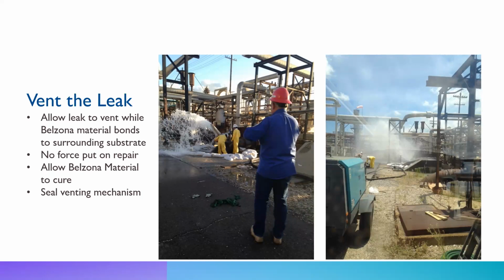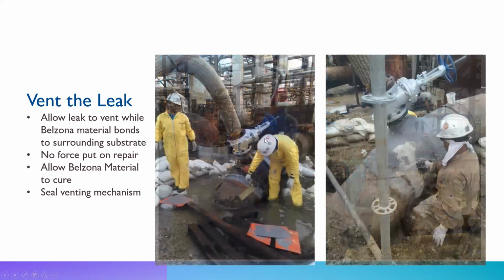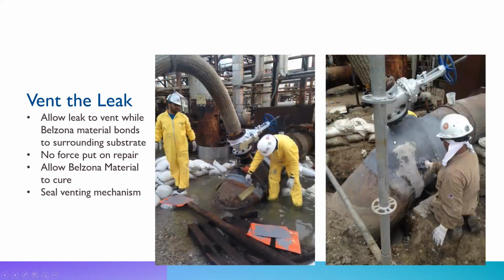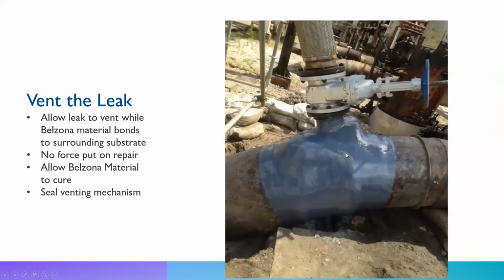Pretty much the way we work is, you call us with a leak and we come out there and we have different ways to fix the leak. So this is one of our techniques, and it depends on the scenario if we're going to use it or not. This is a pretty high flow scenario. So here, a venting plate was pretty much the only option. So they went pretty extensive here and put a valve on it as well with a large nozzle and a hose to divert all the water away. They bonded it down, strapped it down in place, over wrapped it, wrapped it again, and then once everything was cured, they just turned the valve and sealed off the leak.